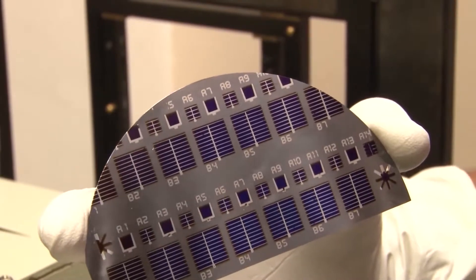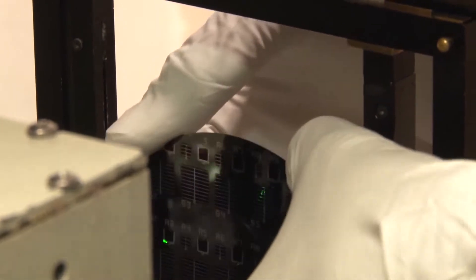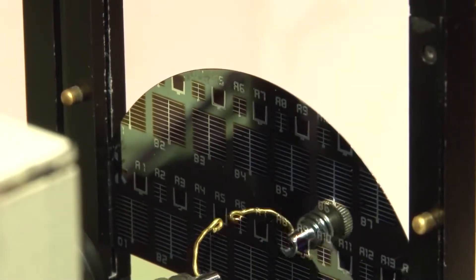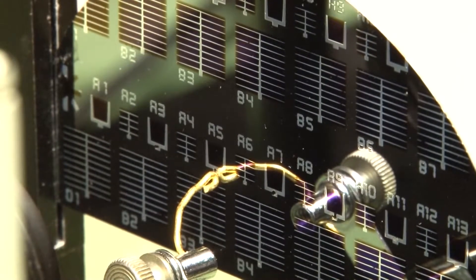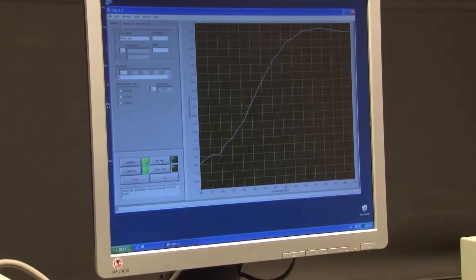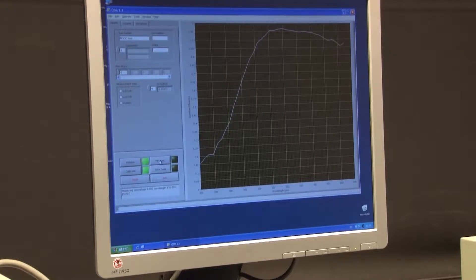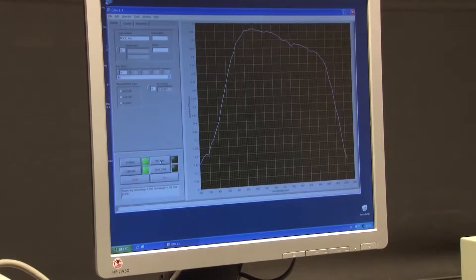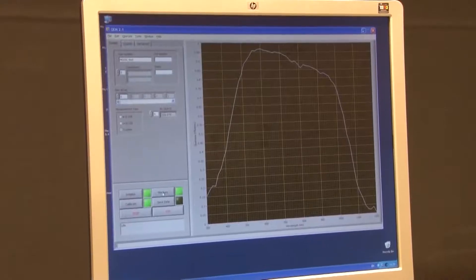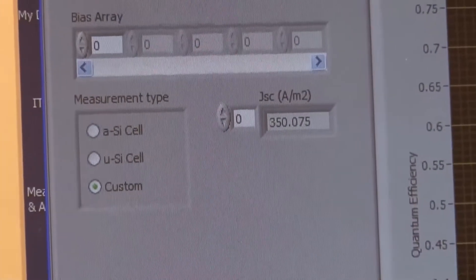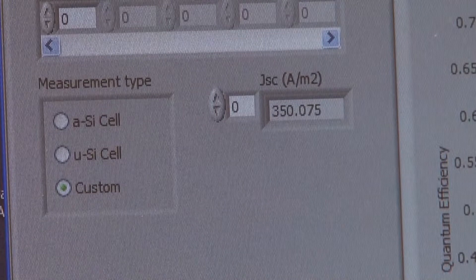As an example, we use a crystalline silicon wafer-based lab-scale heterojunction solar cell. The solar cell is positioned at the same spot as the calibration photodiode, and its contacts are connected to the ammeter to measure the generated current. In this example, we measure the cell under short circuit condition, meaning no additional voltage bias is applied. The external quantum efficiency is measured as a function of wavelength, going from the blue to the red. The EQE can also be measured when additional reverse or forward bias is applied. The measured EQE in combination with the spectral power density of the AM1.5 solar spectrum gives us the short circuit current density of the solar cell. In this case, the current density of the lab cell is 350 A per square meter, or 35 mA per square centimeter.